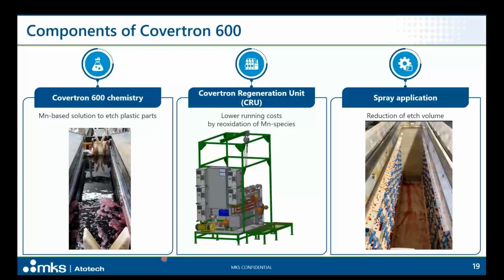So, when we talk about the components of the Covertron 600 system, we need to talk about the chemistry. It is a manganese-based solution to etch the plastic, and you have just seen the way this solution is able to oxidize the plastic resin. We need to talk about a regeneration unit, the Covertron Regeneration Unit, because this unit helps to keep the manganese 7, which you have seen becomes inactive through this autocatalytic reaction. We need to reverse this and bring all these inactive manganese species back to active manganese or permanganate. This is the task of this unit, and it contributes to lowering the running cost. This is very important because, as you have seen from the very beginning of the presentation, for regular production we compulsorily need to work with a reoxidation unit.